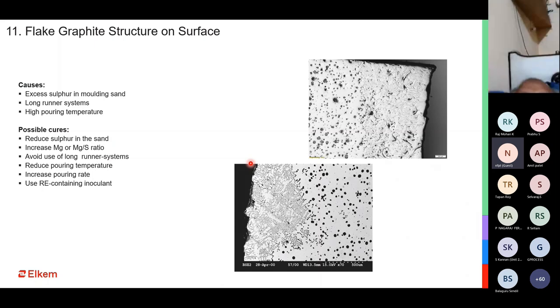So 1:3, if you have magnesium and sulfur, I'm giving you a thumb rule. This is not something which can be directly implemented everywhere, but why I'm telling you a ratio is because if you have high magnesium and low sulfur, it is not good. And if you have high sulfur and less magnesium, that is also not good.